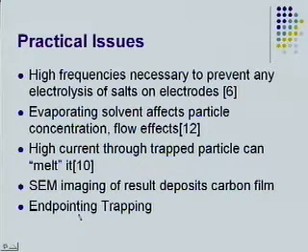like that to image those things, but then once you image them, you can sometimes deposit carbon films or other things like that, so that makes it really hard to measure after you image them. And it also makes it impossible to image them before you actually do the experiment, which makes your controls really difficult. And then obviously we said before that endpointing this is difficult to do.